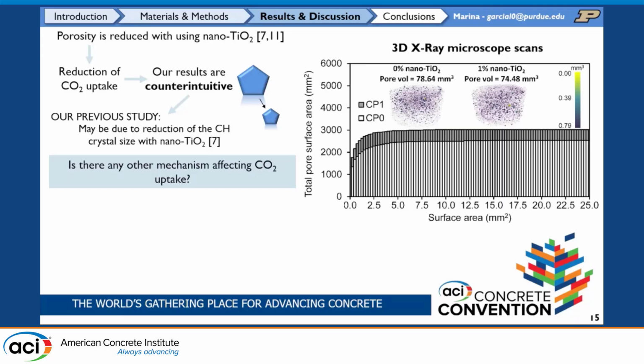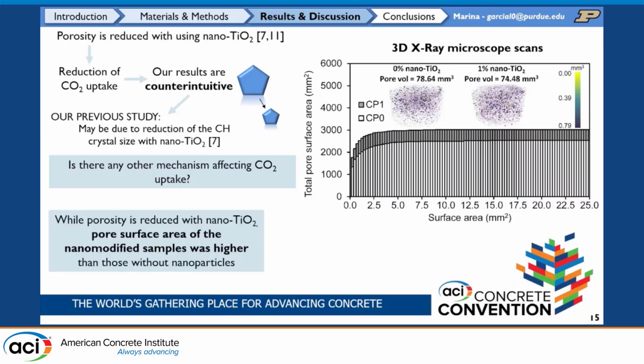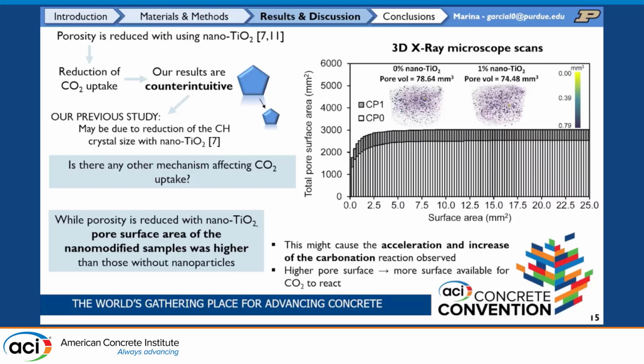So for this, we tested our samples with a 3D X-ray microscope scan. We tested the samples that were not nanomodified and the samples that were nanomodified. And what we saw is that, yes, porosity is reduced a little bit when we add titanium dioxide nanoparticles, but the pore surface area of the pore structure is increased. So this may cause this acceleration of the carbonation process because we have higher pore surface area, so the CO2 has more surface to react with.